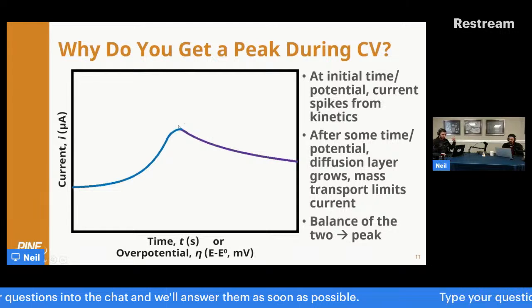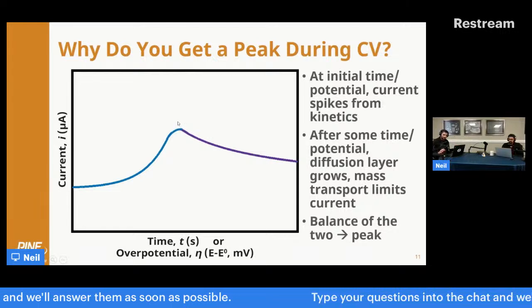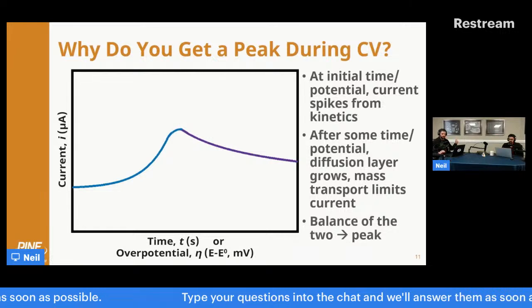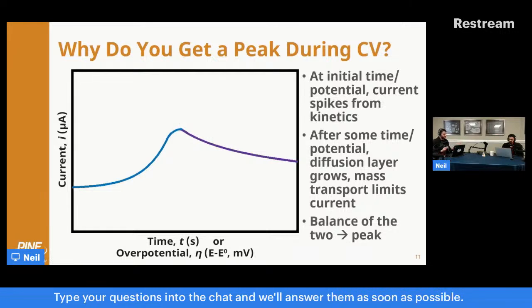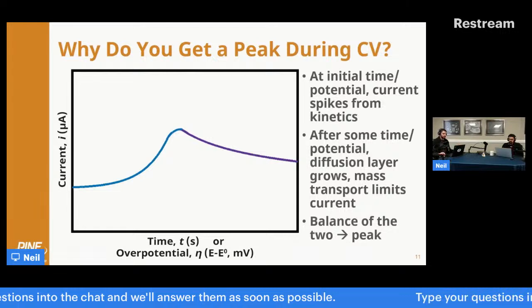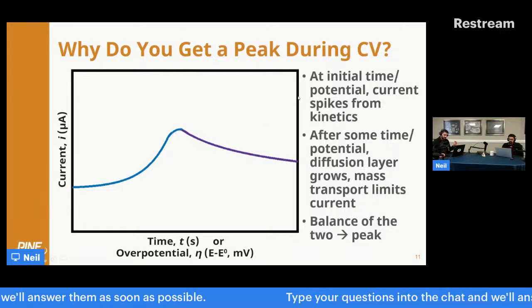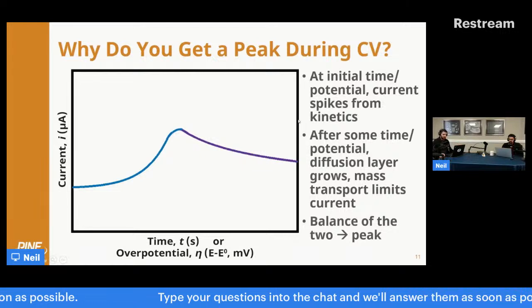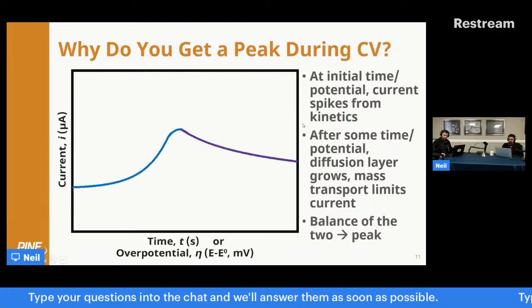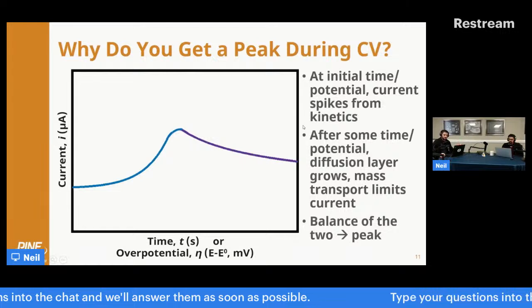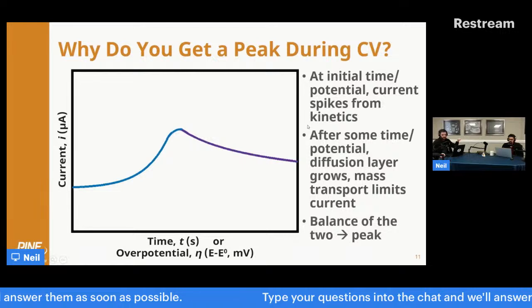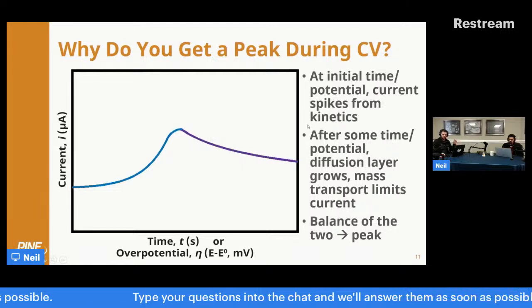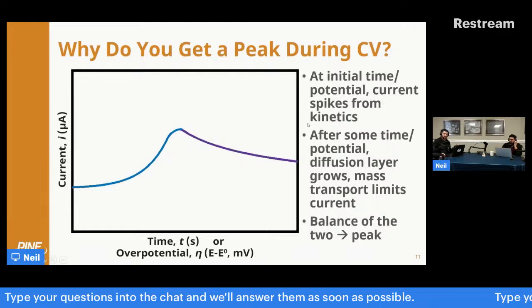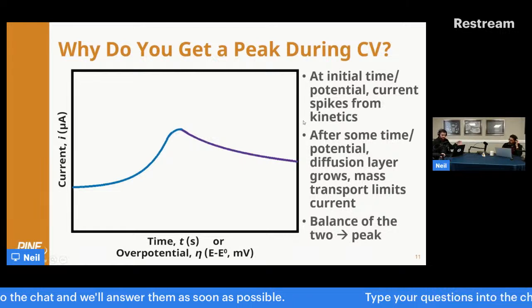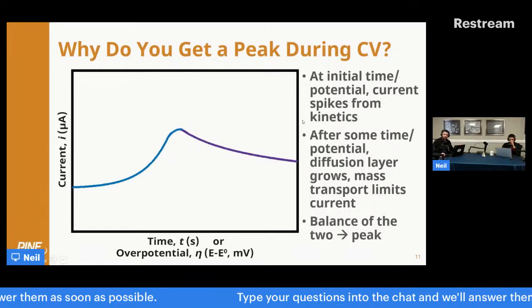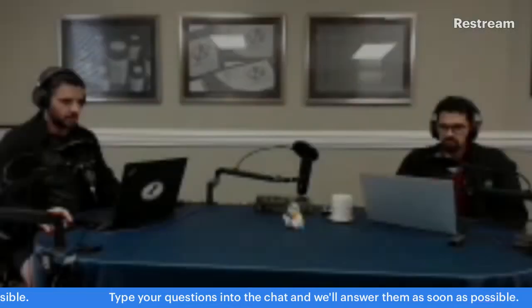There's a lot more, of course, that there's equations that describe where that peak is and why and how much current it is in the Randles-Sevcik equation and scan rates. There's a lot more there, but fundamentally, that is the explanation I can give you for the appearance of a peak when you do cyclic voltammetry under stationary conditions: you have a kinetic increase in current, the diffusion layer thickness grows, and diffusional effects cause the current to decay. And so a peak is just the natural graphical consequence of those phenomena.